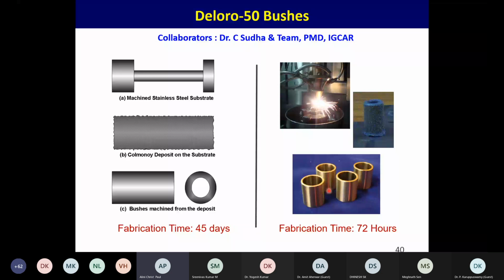What happens is, in nuclear reactors, when materials are exposed to high temperature and pressure, and they stay for a very long time, then they have a tendency to weld themselves, and this effect is called galling. And when you want to use it, it may not perform the operations. So to come out of these issues, people use some anti-galling materials, and Deloro 50 is one of the materials which is used. And the problem with this material is that it is a very hard material.